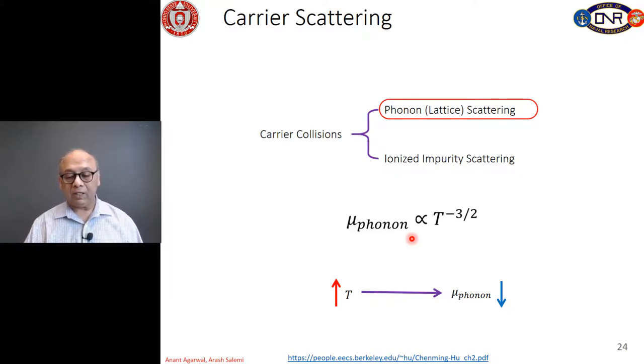One is called the lattice scattering, or a more fancy name is phonon scattering. This means the electrons are colliding with the silicon atoms, which are periodically placed in a cubic silicon lattice. And then the second type of collision event is with ionized impurity. So if you have doped it with N-type, then you have a lot of positive donors, which will have a Coulombic attraction to the electron, and that's called the ionized impurity scattering.